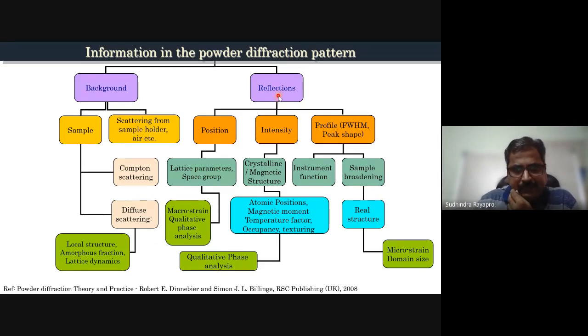And the reflections, or the Bragg peak positions, can tell you about the position, the intensity as well as the peak shape. The position will tell you about the lattice parameters or space group of this sample. And if you carry out microstrain analysis, you can also carry out qualitative phase analysis using the lattice parameters and space group information. The intensity of the peak can be from the crystalline or magnetic structure. And it has information on atomic positions, magnetic moment, temperature factor, occupancy, texturing, and so on. And by using qualitative phase analysis, you can understand what this is all about.